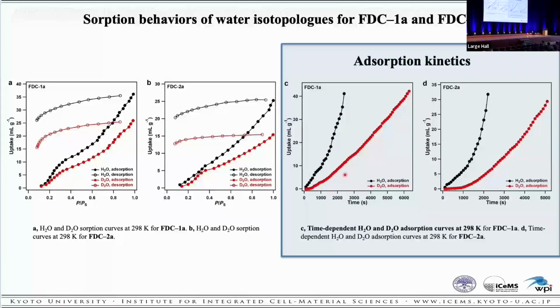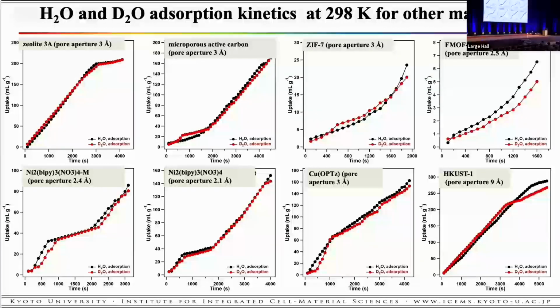These are the adsorption kinetics curves for water isotopologues in the FDC system. On the left are the pressure-dependent desorption curves. On the right are the time-dependent adsorption curves. The results show that H2O diffuses faster than D2O, and the adsorption rate clearly indicates that the molecule is recognized. We carried out control experiments for other small pore adsorbents, zeolites, ZIF-7, FMOF, other metal compounds, and so on. All these show negligible difference in the adsorption kinetics of water isotopologues.